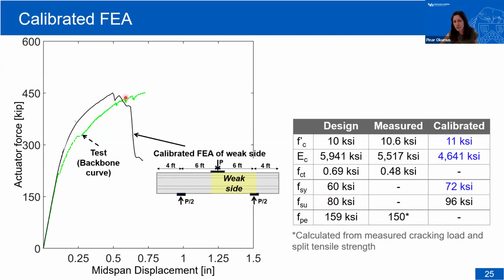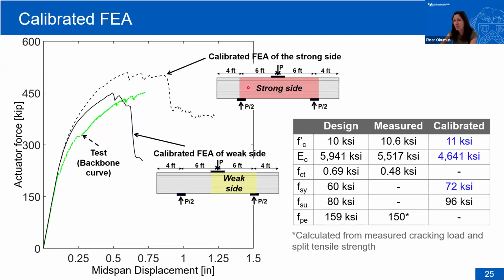The reason why the post-cracking stiffness doesn't match is because we're using cyclic test data but monotonic loading for the finite element analysis. If we compare the last cycle, they actually match, or if we model the last cycle, they match much better. So that's our calibrated FEA. We then model the strong side to get the failure load with that calibrated FEA. So this is our failure load that we obtain and mix with our test data for retraining.